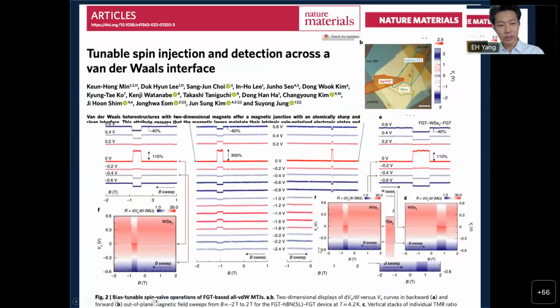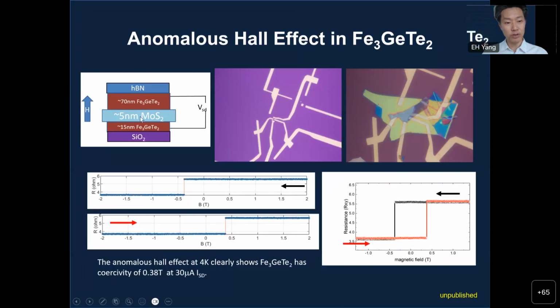So we did that, and basically we decided to copy this work and see how it works. It's not an exact copy, but kind of similar, because they use FGT and then tungsten disulfide. In our case, we use FGT and then molybdenum disulfide. So it is different but similar. We use this structure. Basically, you apply current like this, and then we measure the voltage here. That's the Hall sensor, basically. And then you see this anomalous Hall effect, and that's exactly what is shown.